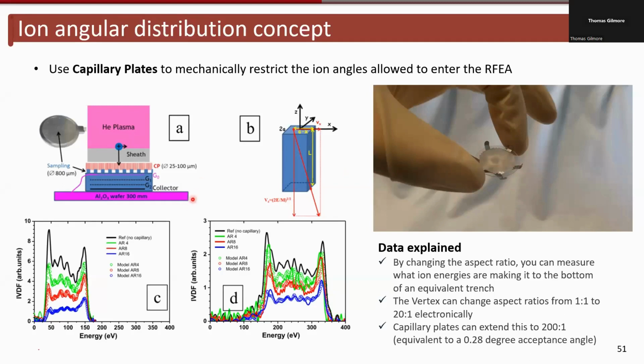You can get these made in all sorts of different dimensions. And what happens is you can measure an ion angular distribution where there's no plate on top, and that has a 45-degree acceptance angle. But then as you place different plates on top with different aspect ratios, you can measure what the ion energy distribution function would be like after it gets to the bottom of that trench, of that depth, or that aspect ratio. I do need to show one more step to this, so bear with me a moment.